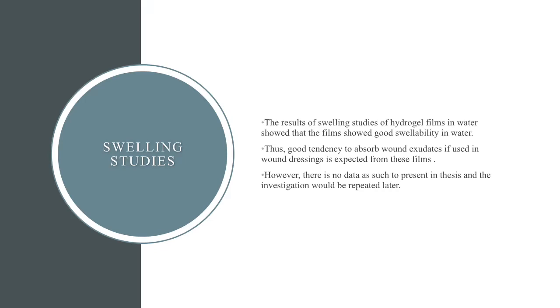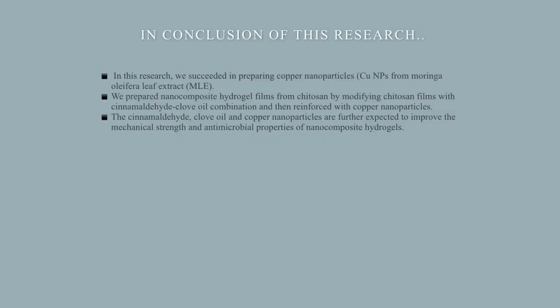Let's get to the results of swelling studies of hydrogel films in water, and it showed that the films had good swellability in water, thus a good tendency to absorb wound exudates is expected from these films if used in wound dressing. However, there is no data as such to present in the thesis, and the investigation would be repeated later. In conclusion of this research, we succeeded in preparing copper nanoparticles from Moringa oleifera leaf extract. Also, we prepared nanocomposite hydrogel films from chitosan by modifying chitosan films with a cinnamaldehyde and clove oil combination and then reinforced it with copper nanoparticles. Lastly, the cinnamaldehyde, clove oil, and copper nanoparticles are further expected to improve the mechanical strength and antimicrobial properties of the nanocomposite hydrogels.